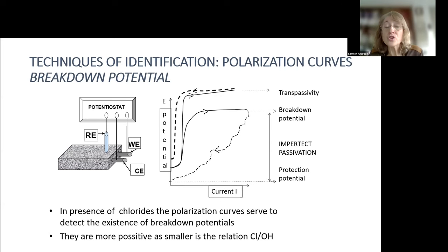And as I was mentioning before, it depends very much on whether you use, for instance, polarization curves, and even the speed of the polarization curves, that the value of the chloride content changes. In that case, it's very important to link the value given by these electrochemical techniques to the technique itself, because the chloride threshold changes depending on the conditions.